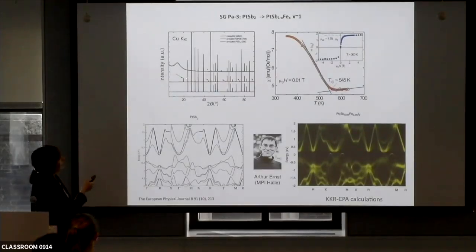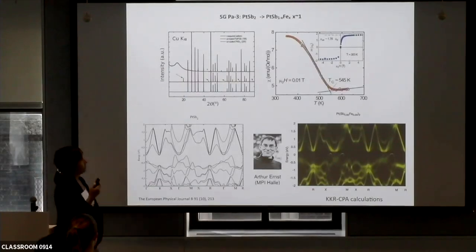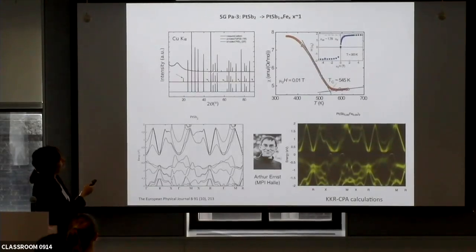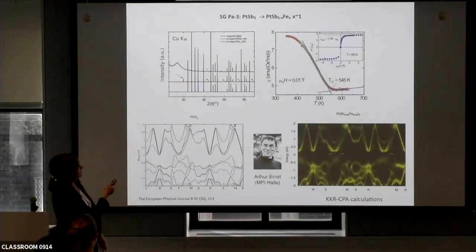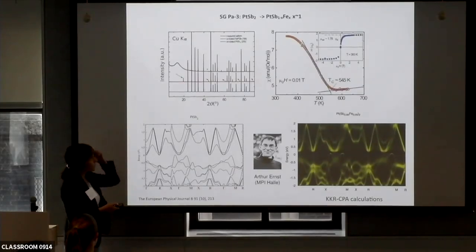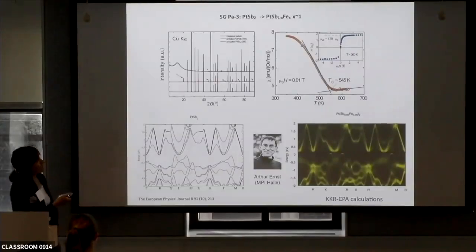And the blue one is the simulation for another space group. So the little peaks here that we don't find in the blue line are actually very important, and what we really measured, the phase that actually holds the compound, is not the chiral space group, it's a non-symmorphic space group Pa-3, with a glide and inversion.